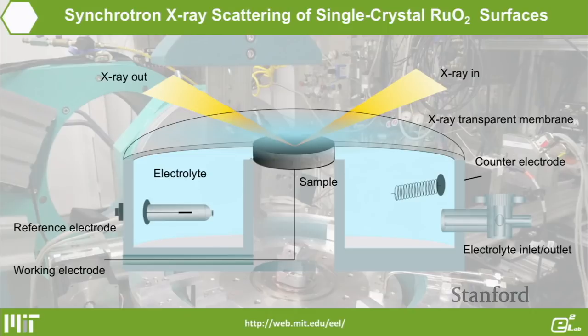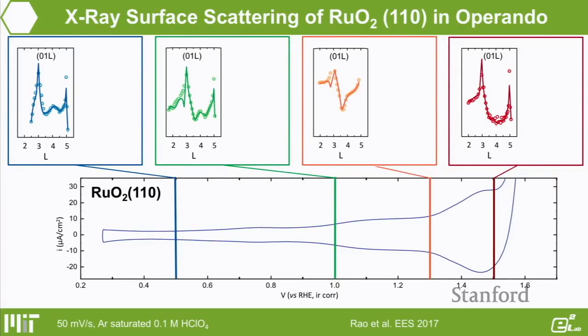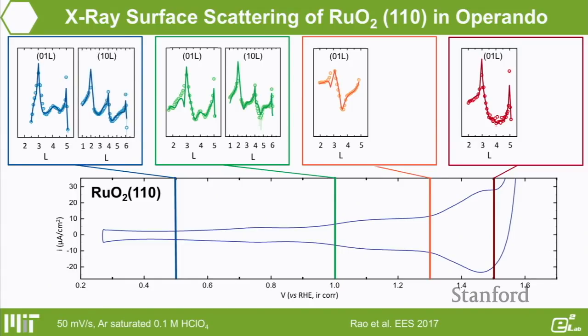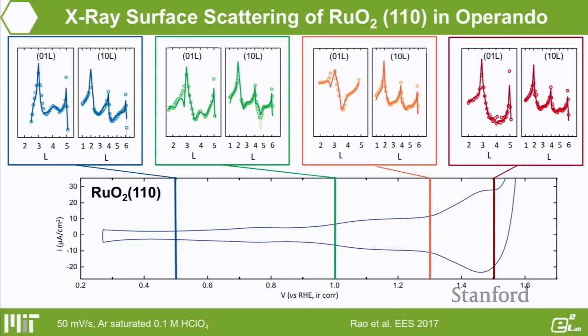So we utilize these in situ flow cells on the synchrotron. Then you can actually look at a single crystal surface, how it changes as a function of potential. So essentially, this is a CV, a cyclic voltammogram, of the ruthenium dioxide 110 surface, and at different potentials, essentially you can collect crystal truncation rod spectra, which is really just in situ surface diffraction. And you can actually collect a rod, let's say a rod of the 01L type, you can see the rod spectra are actually changing as a function of potential. It means it's sensitive to the surface changes. It's a rod that's very sensitive to the scattering of oxygen. And similarly, if you look at the 10L rod, it's also changing as a function of potential.